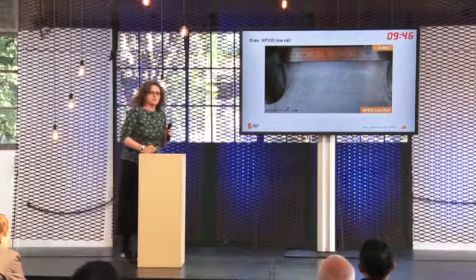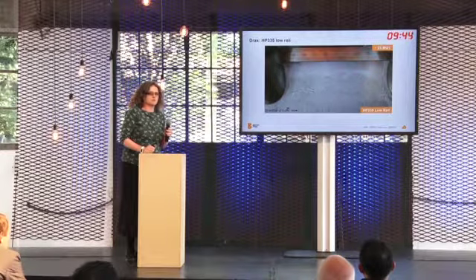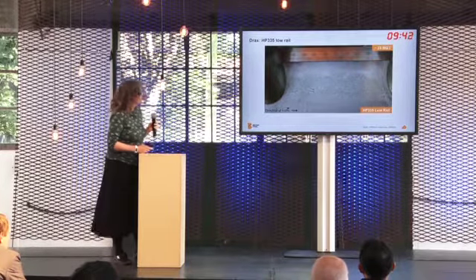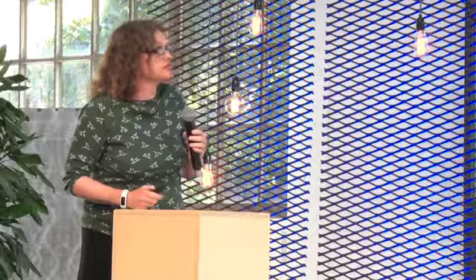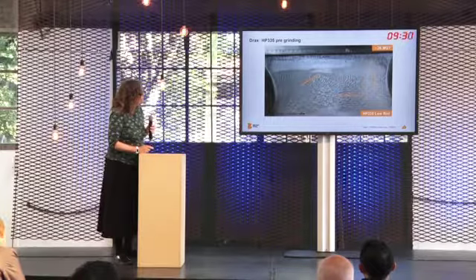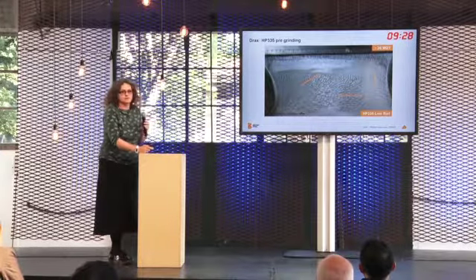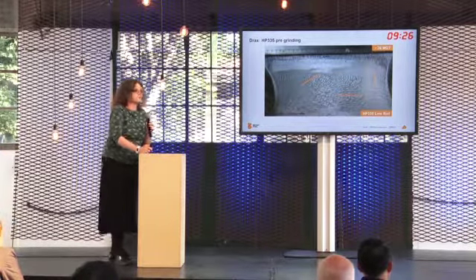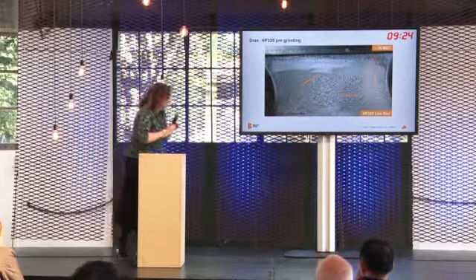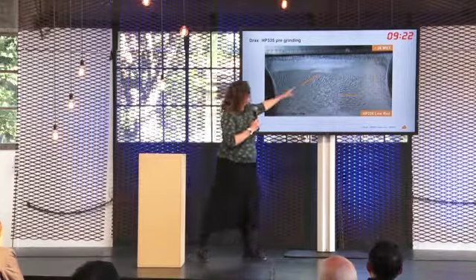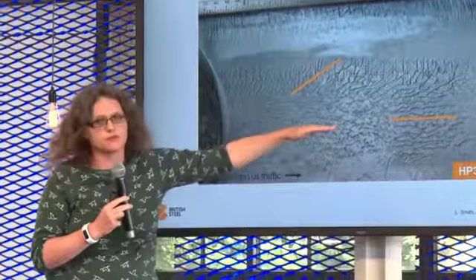23 million gross tonnes, so I approximately go back every 3 months to this site. We started to see some more developing around the centre of the head. I typically call this snakeskin effect, which is low rail rolling contact fatigue. 26 million gross tonnes, we can see that there was some more developed on the HP335. You've got sort of 3 strains.